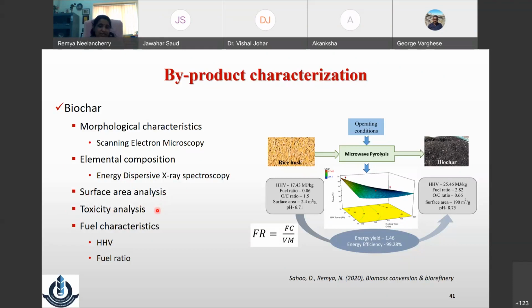Or if you are using it as an adsorbent for water treatment or wastewater treatment, the biochar should not add any toxic material to your water sample. So that way toxicity should be tested. And you can also use this biochar as a heating fuel. So in that case, the HHV and fuel ratio, which is the ratio of fixed carbon to volatile matter, can also be assessed.